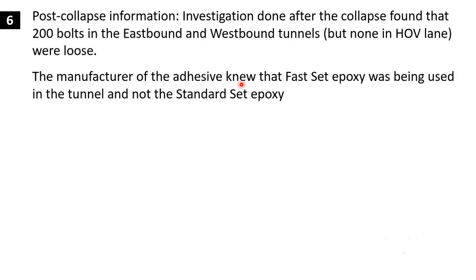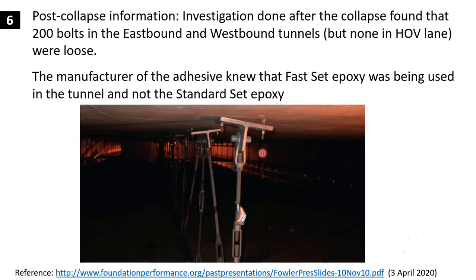The manufacturer of the adhesive knew that fast set epoxy was being used in the tunnel and not the standard set epoxy. So the manufacturer had the knowledge that fast set epoxy was inferior, but it was being used in the tunnel. Here you can see in this picture a bolt which has already come out of the concrete of the roof. So this kind of loose bolt was found in the tunnel during the investigation.